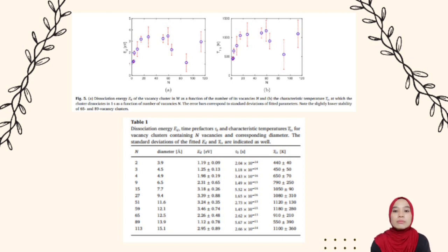Consequently, they observe lower stability of vacancy clusters. Moreover, molecular dynamics and KMC use completely different timescales and also different criteria to distinguish dissociation and rejoin events. A dissociation criterion of 100 steps is used, but these KMC steps are variable and temperature dependent.